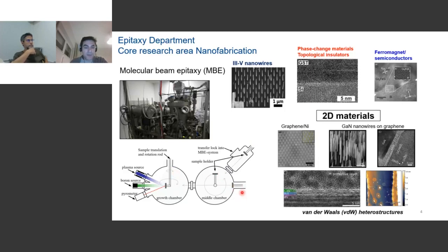And the middle chamber is also a place where you usually will then perform sample treatments like annealing before growth, because you want to really clean the surface of your substrate. You want to remove water or any other sort of contaminant. You may also perform other types of treatments like sputtering and different things that you can do at the middle chamber, so that when you move your sample to the growth chamber, the surface of the substrate you want to grow on is ready for the epitaxial growth.